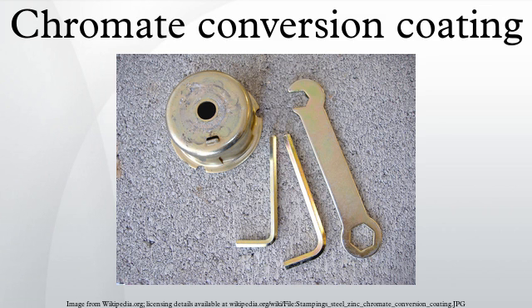Composition: the composition of chromate conversion solutions varies greatly, depending on the material to be coated and the desired effect. Most solution formulae are proprietary. The widely used Cronak process for zinc and cadmium consists of 5 to 10 seconds of immersion in a room temperature solution of 182 grams per liter sodium dichromate crystals and 6 milliliters per liter concentrated sulfuric acid. Iridite 14-2, a chromate conversion coating for aluminum, contains chromium trioxide, barium nitrate, sodium silicofluoride and ferricyanide.